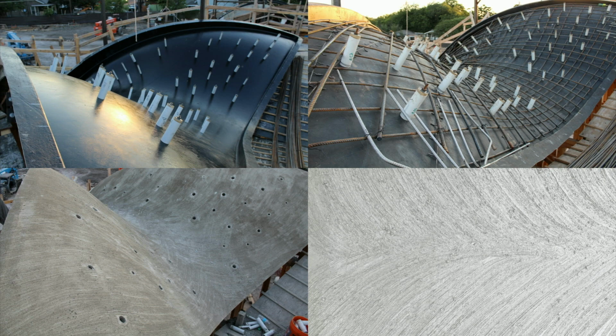In order to have the petals resonate with the flow of water, even when it was not raining, the open top side of each petal was broom finished with the direction of the broom aligning with the flow direction of the water. In effect, the top surface of each petal is one giant valley covered with a network of small valleys produced by the bristles of the broom. Over time, this textured surface of the broom finish concrete will reveal the flow of water as various airborne matter such as pollen, dust, and bird droppings collect on the broom finish and stain the concrete as water runs across the surface.